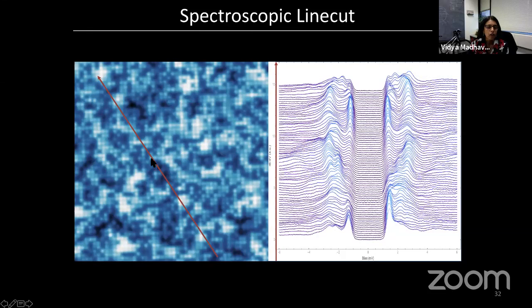If you were to march along this line and obtain a spectrum at equal intervals, this is what you get. Let's just focus on the first spectrum here. You can see the density of states does go to 0. This is 0, and these others have been offset, but the first one is not. So you have 0 density of states, like you would expect in an S-wave superconductor. You have these coherence peaks, which are particle-hole symmetric. They tell you the magnitude of the gap.